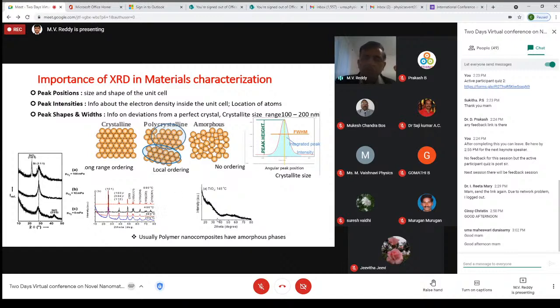So remember, if it is thin films or amorphous, we get broadened lines. We don't see sharp lines due to no ordering and local ordering, unlike polycrystalline and crystalline materials. Depending on peak position, size and shape, and also peak intensity, we can do a lot. By knowing the full width at half maxima, we can tell that your materials are nano size or nanocrystalline size. So this is one way. Without going to TEM, we can calculate the average nanocrystalline size by using X-ray diffraction.